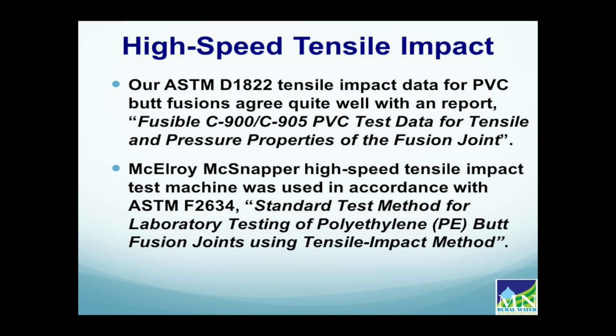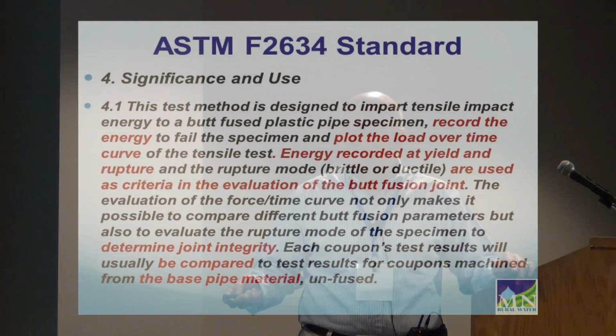Our tensile impact data for the PVC butt fusions agreed quite well with this report that is in the literature, fusible C900-905 PVC test data and pressure properties for a fusion joint. For this particular report, the laboratory used a McElroy McSnapper high-speed tensile impact test in accordance with the ASTM test method, the standard test method for laboratory testing of butt fusions. They used the same test method for PVC, which is perfectly fine — there's nothing wrong with that at all.